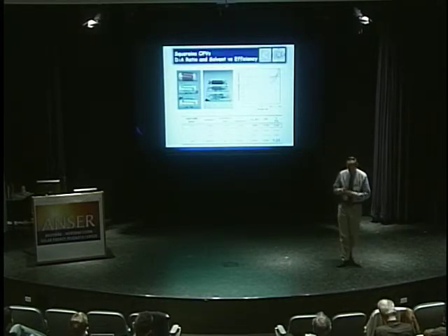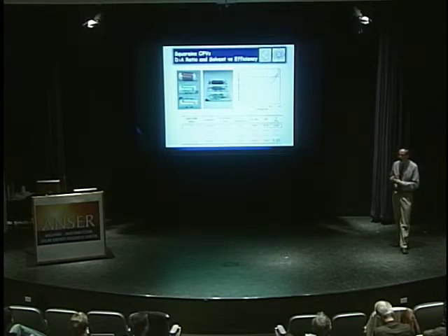And what you see are fairly large open circuit voltages, quantum efficiency of 1.25%. This is going to require a lot more modification and experimentation with the processing conditions. Quen Yuen at University of California at Santa Barbara has another small molecule system, and she recently reported efficiencies on the order of 3%. So there's some really interesting possibilities for small molecules. They're easier to make, easier to purify, easier to handle.